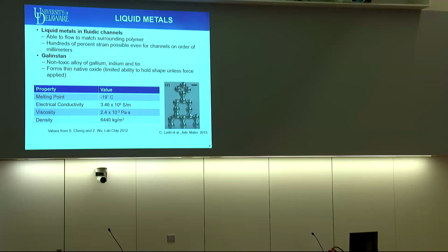A lot of my own work's using another liquid metal called Galinstan, very similar to the eutectic gallium indium this morning, very similar in properties and so on. But this is a eutectic alloy or eutectic combination of gallium, indium, and tin. And it again forms this thin native oxide, which has a number of advantages. From the perspective of a lot of devices we're working with here, the main one is that once they're in place, they don't easily leak out of the material. You have to apply an active pressure to push them out of a channel. And they also can be considered in some cases self-healing for that reason.